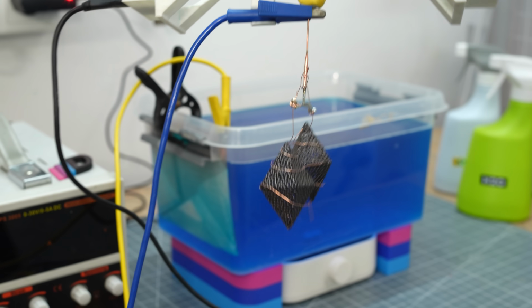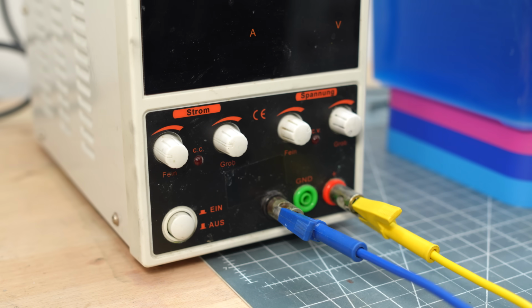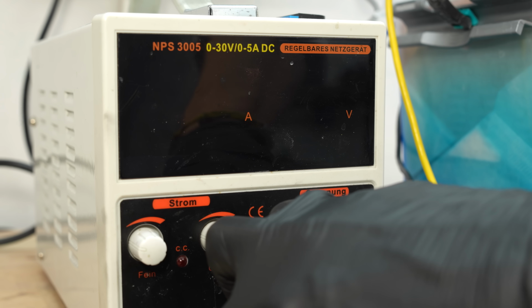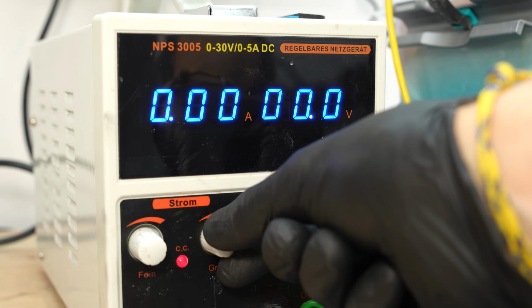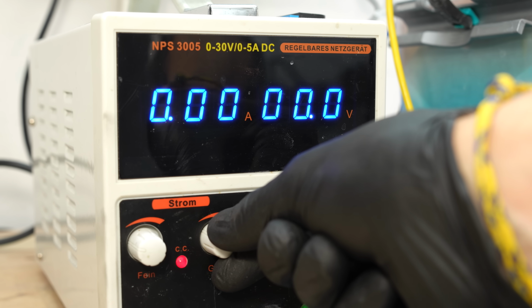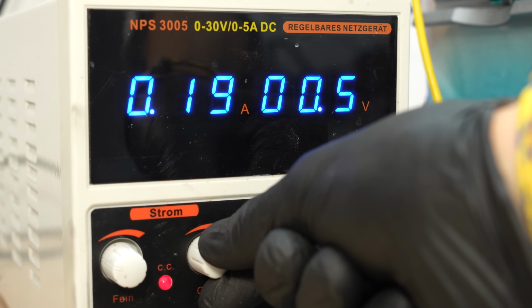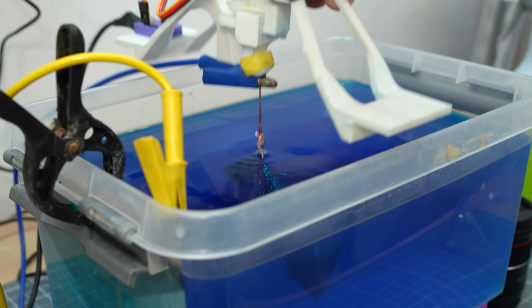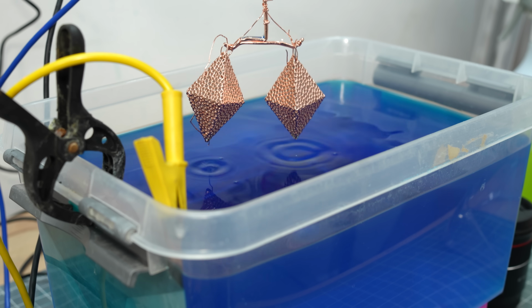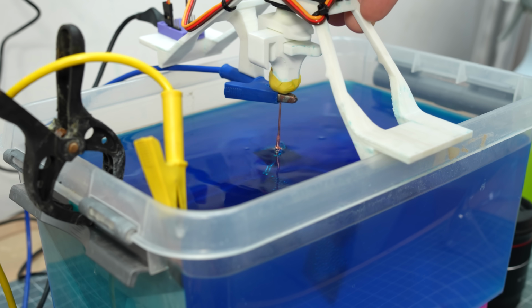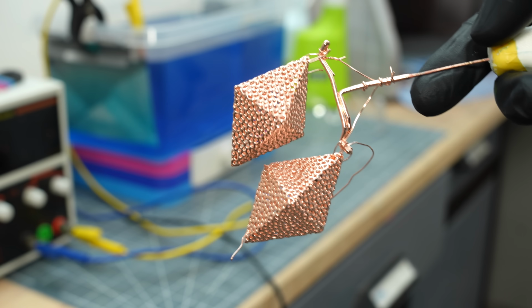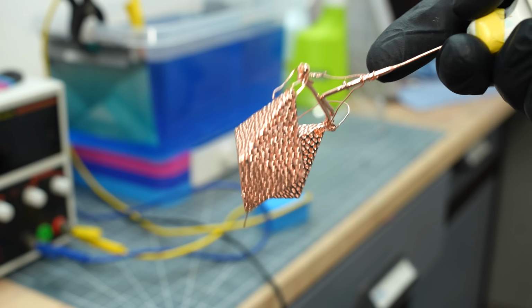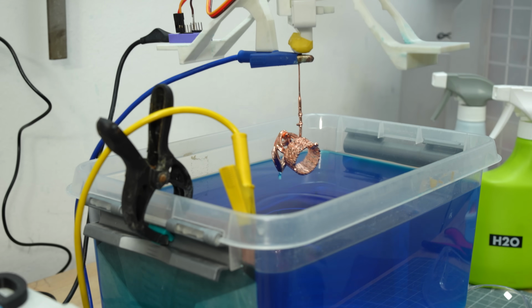I connect my rotary jig to the negative terminal and immerse it in the electrolyte. Then I set the power supply to constant current mode and coat at 1 amp per square decimeter for 4 hours. A shiny copper layer forms relatively quickly. You can check it occasionally, and if everything looks good, you continue. Afterward, I rinse it with distilled water. I repeat this process for all the remaining pieces.